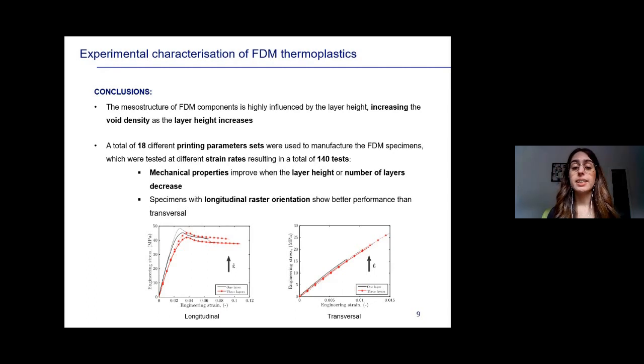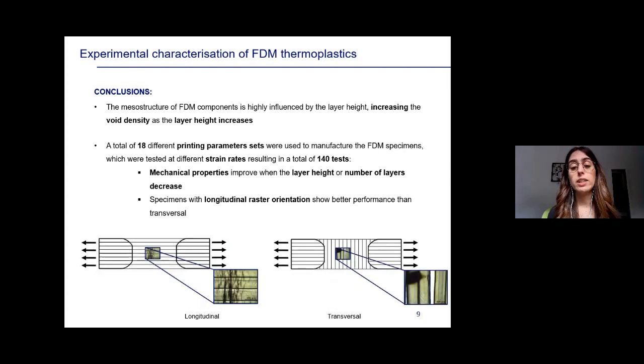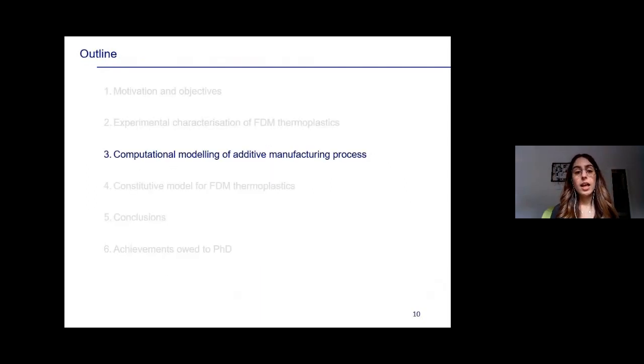Analyzing the mechanical behavior of these materials, we observed that the mechanical properties improve when the layer height and the number of layers decrease, and also that the behavior is completely different if we compare a longitudinal raster orientation with a transversal one. That's not only in the stress-strain response, but also in the failure. While longitudinal specimens present a ductile failure, the transversal ones present a brittle one. Now I will continue with the second part of my research.